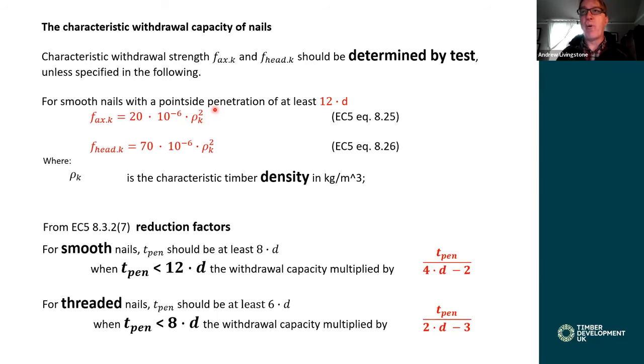The following criteria are: the point side penetration should be at least 12 times d, to calculate using axial withdrawal, head side pull through. However, reduction factors may come into play. For smooth nails, the point side penetration should be at least 8 times the outside diameter. However, when the point side penetration is smaller than 12 times the outside diameter, the withdrawal capacity should be multiplied by this reduction factor here. And for threaded nails, that could be helicoidal or screws, and so forth, again, the point side penetration should be at least a minimum of 6 times the diameter, but when it is less than 8 times the diameter, we multiply it by this reduction factor here.